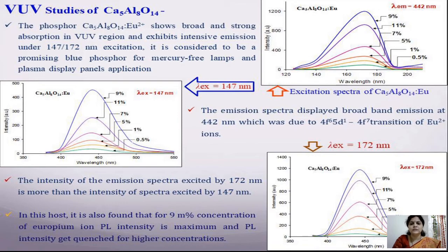The emission spectra display broadband emission at 442 nanometer, which was due to the 4f6 5d1 to 4f7 transition of Eu2+ ion. The intensity of the emission spectra excited by 172 nanometer, that means the last graph, is more than the intensity of the spectra excited by 147 nanometer. In this host, it is also found that for 9 mole percent concentration of europium ion, PL intensity is maximum, and PL intensity gets quenched for higher concentration.